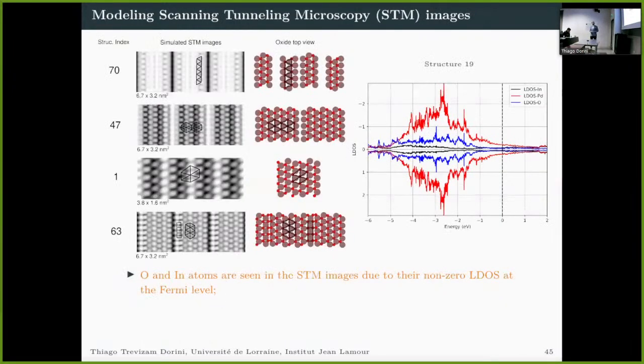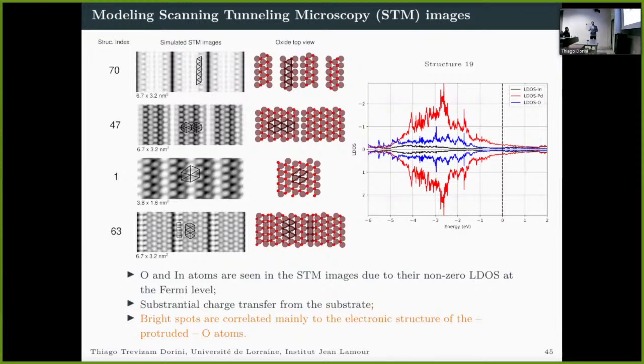In addition, we have simulated the STM images for all the phases that we've calculated, so that we can see what their properties are. What you can see in the STM image is the electron density of oxygen and indium atoms, specifically, because there is a non-zero local density of states at the Fermi level in these phases. And this happens, as I said at the beginning, due to the charge transfer between the metallic substrate and the oxide. More precisely, the bright spots that we see in the STM images correspond specifically to the electronic structure of the protruded oxygen atoms, because they are above the mean height plane of these oxides, so it's easier to see the electronic density of these atoms.